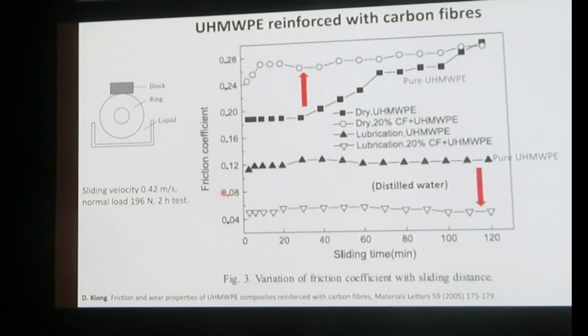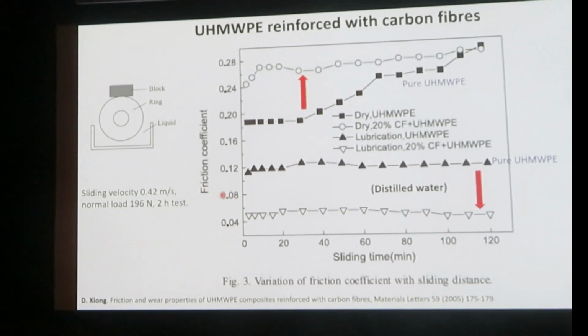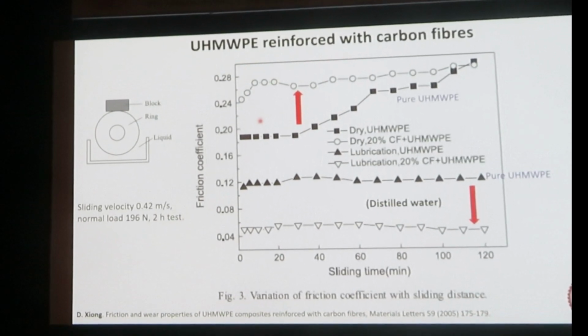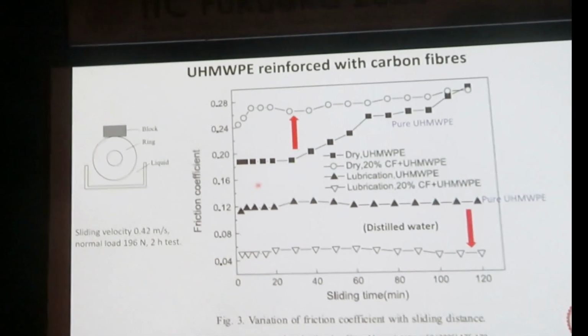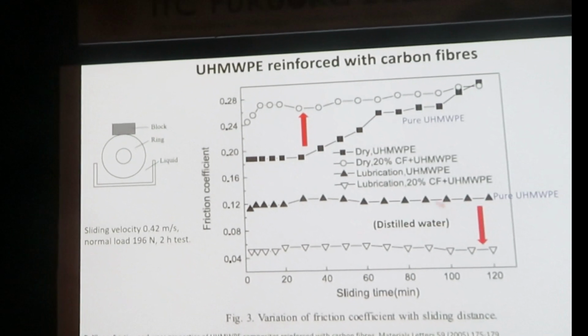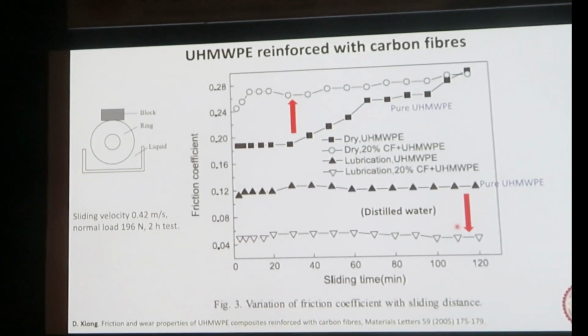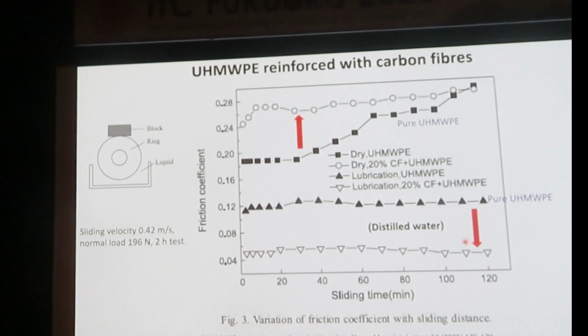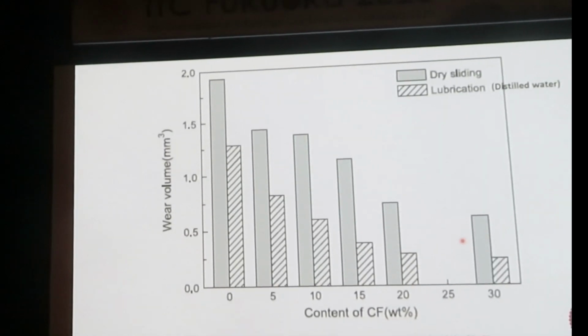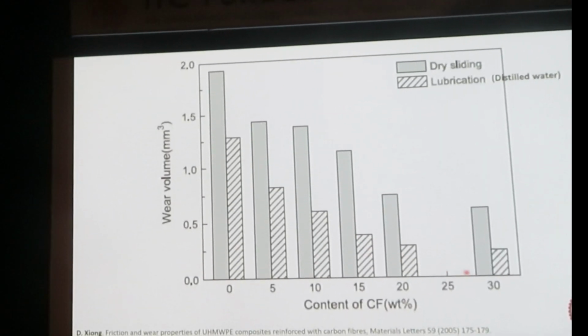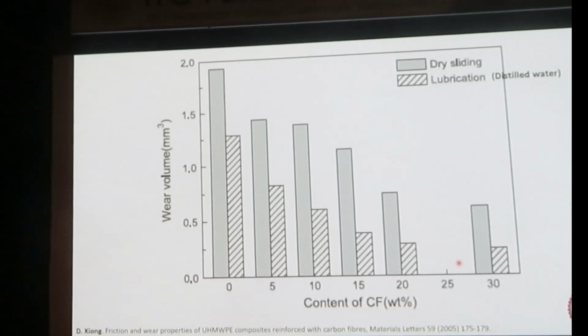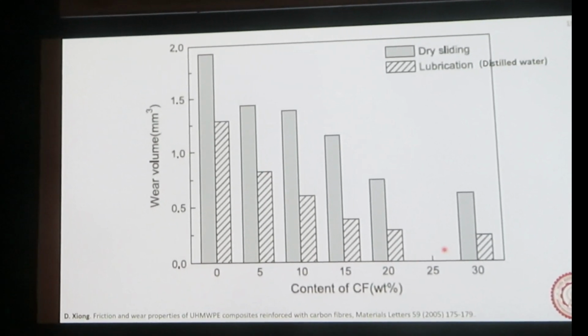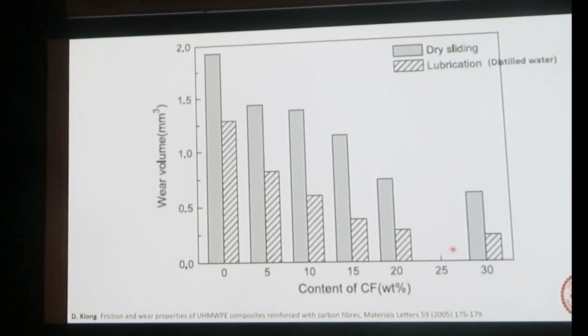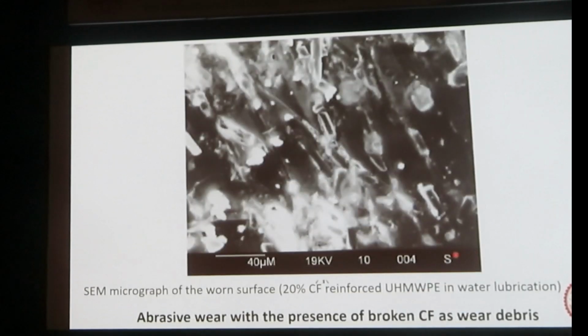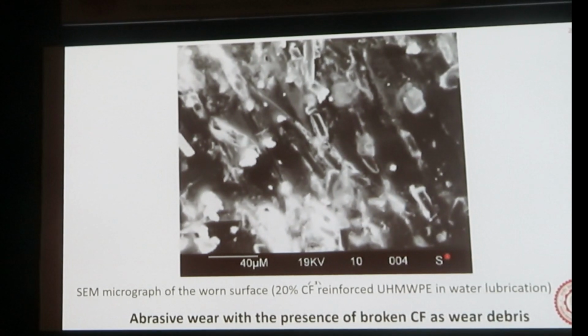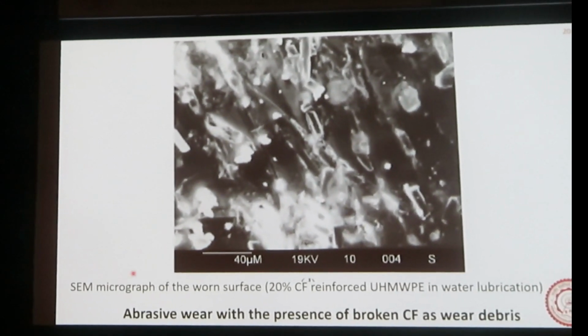Then what about fibers? Some people have tried fibers, for example carbon fiber reinforced UHMWPE. This work was done only in distilled water, but still you can see further improvement in the coefficient of friction, as well as some improvement in the wear. So after adding carbon fiber, you can improve the wear rate even in the lubricated case as well as in the dry case. But the wear failure is of some worrying nature.